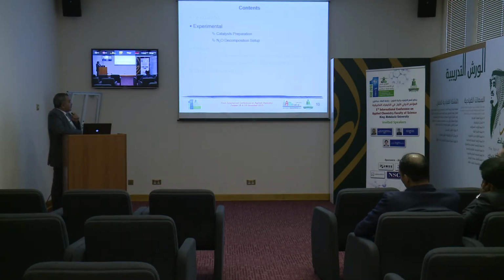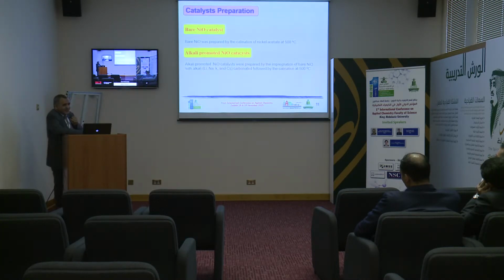Going to the second part, which is the experimental. Regarding the catalyst preparation, neat nickel oxide or bare nickel oxide was prepared by the direct calcination of nickel acetate at 500 degrees Celsius, and the alkali promoted nickel oxide catalysts were prepared by the impregnation method, in which the required amounts of lithium, sodium, potassium, and cesium were mixed with the required amount of nickel oxide and calcined further at 500 degrees.